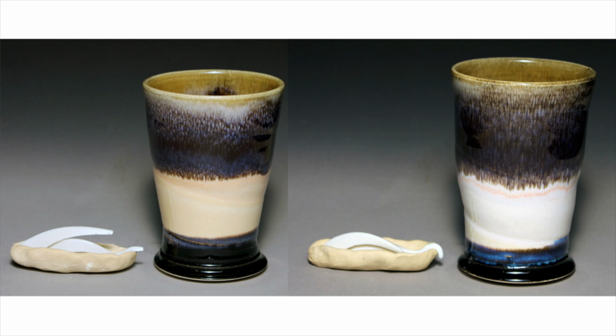Temperature differences throughout the kiln are another factor. Almost all kilns have hotter and cooler areas. These two cups were glazed with the same glazes at the same time and fired in the same kiln. The left one was placed in the bottom and the right one in the top. I often place pieces with a particular glaze in one part of the kiln and another glaze in another part. Again, experience is the best teacher.